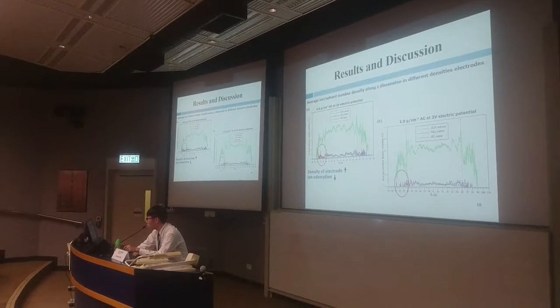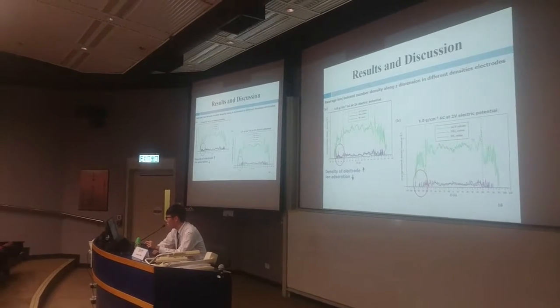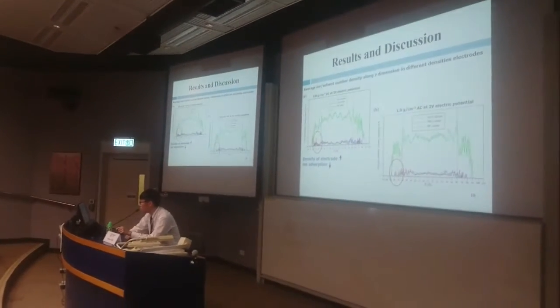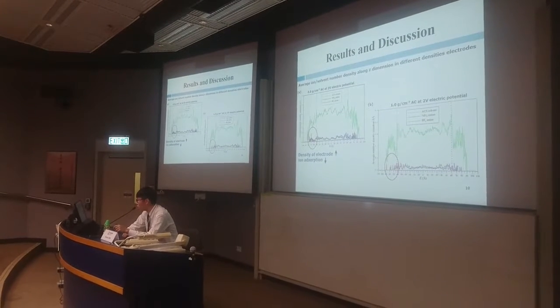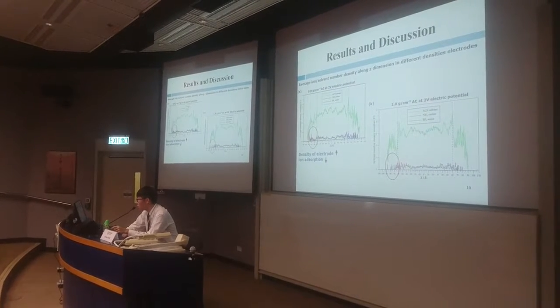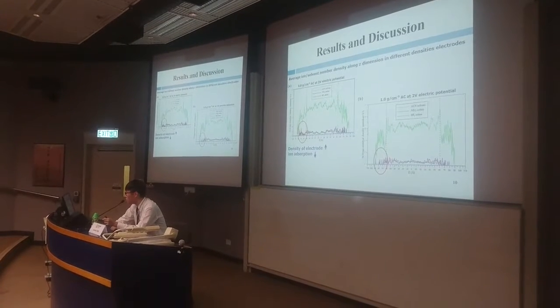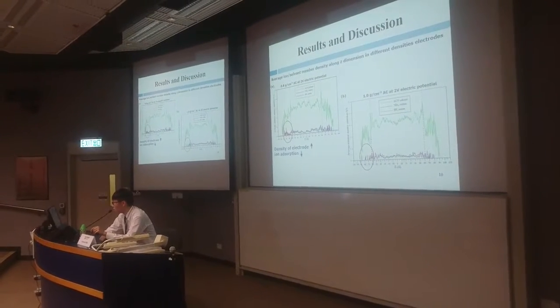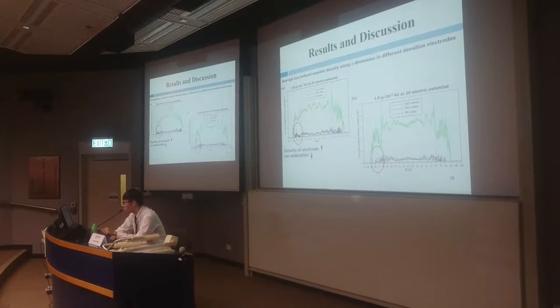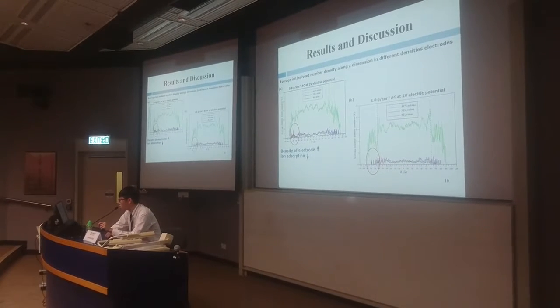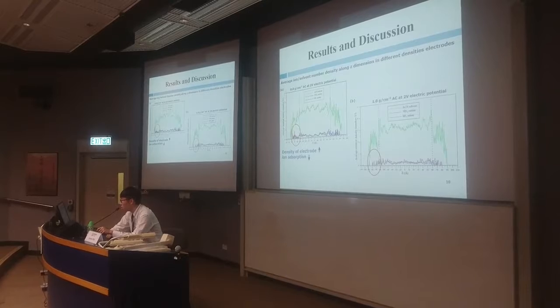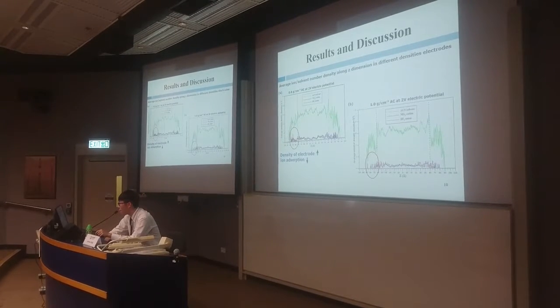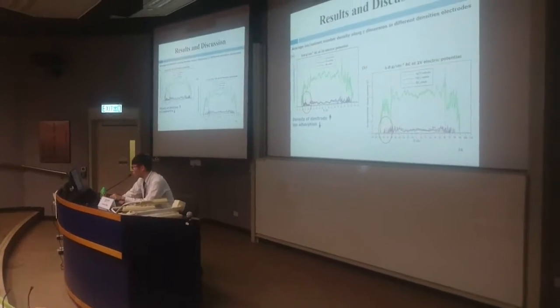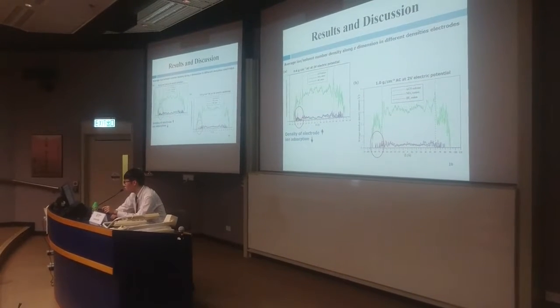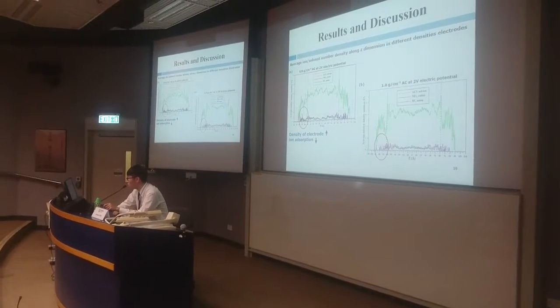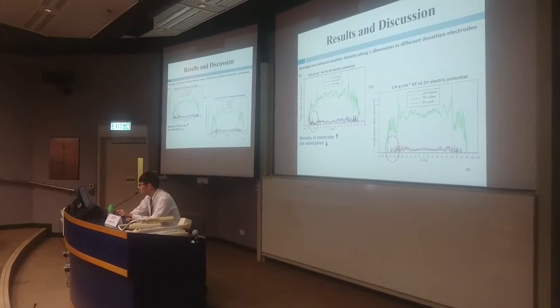These two figures show the average number density of ions under the 2 V electric potential. So we can see that the ions are attracted to the electrodes due to the strong Coulomb interaction, and there is not much number exchange at the electrode interface.